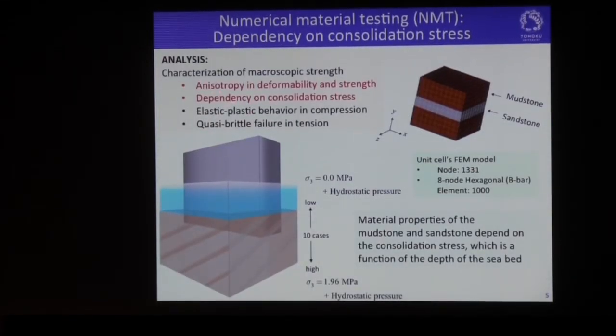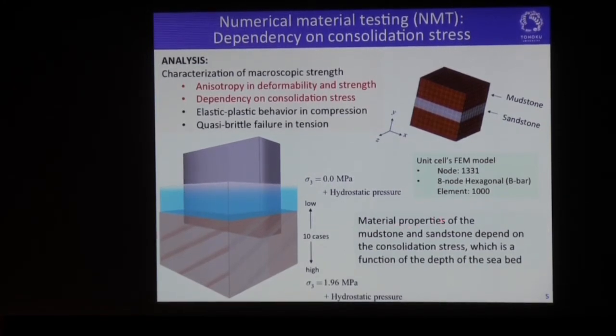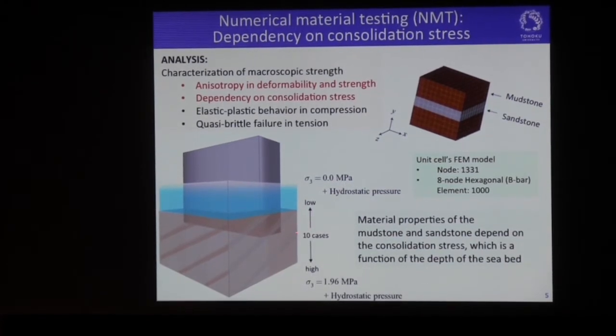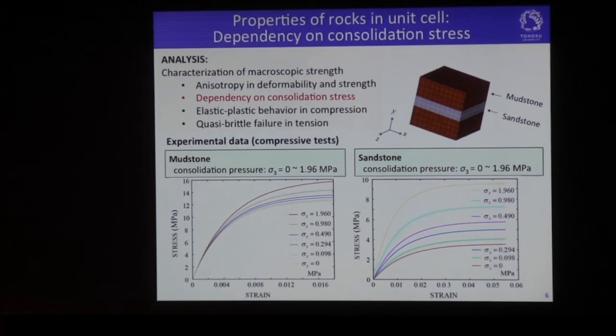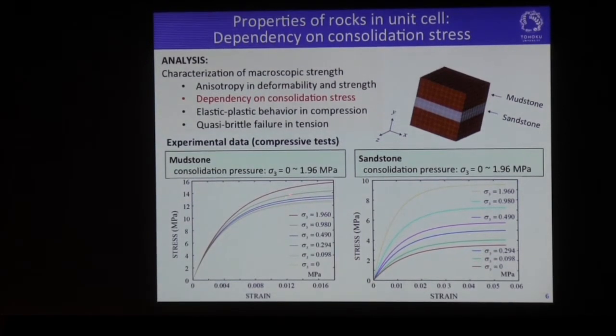Then, as I mentioned, we have to consider the anisotropy in deformability and strength, and also the dependency on the consolidation stress. That is, we have to consider the material property that depends on the consolidation stress, which is a function of the depth of the seabed here. This is the intake tower, this is the seabed. So this slide shows the typical stress-strain curve of the mudstone and sandstone, which exhibits the dependency on the consolidation stress. As you can see, the flow stress of this curve is increased as the consolidation stress is increased.